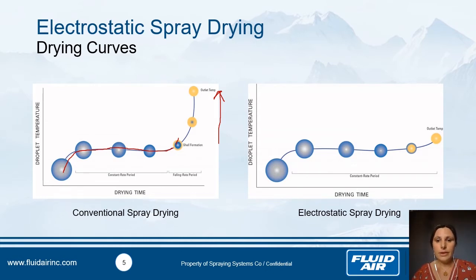In the case of the electrostatic spray dryer, what happens? When we apply a charge, we help the water to diffuse really well in the droplets, so we don't keep water in the middle. We help the water move to the surface, which means we don't need high energy to evaporate it. Moreover, you create a thin layer of water around the droplet, and like that you can protect your active during the drying. That is something new. The most important parameter now is not the inlet temperature but the outlet temperature, and how to manage it to assure good drying of thermosensitive compounds.